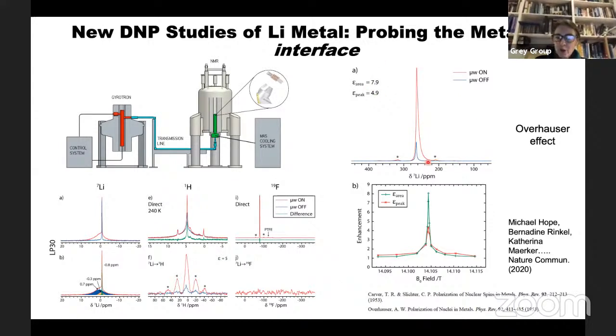So what you're looking at in blue is the lithium signal. And then when you turn the microwaves on, so the microwaves are tuned so they hit the electron resonance, you get a signal enhancement of, in this case, about 8 times. And so it's interesting, we can do things with it. What is really interesting is we can then transfer magnetization from the electrons to the inorganic components on the surface of the lithium metal, so the inorganic components of the lithium SEI interface.